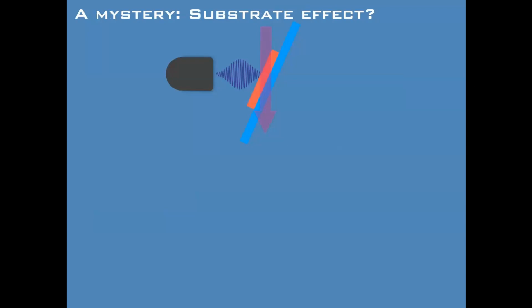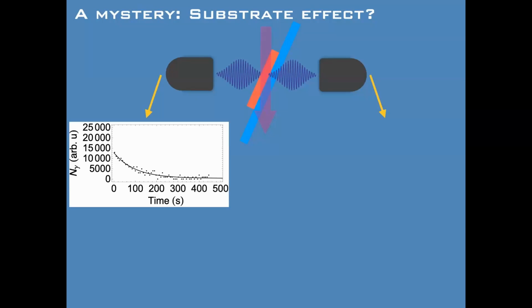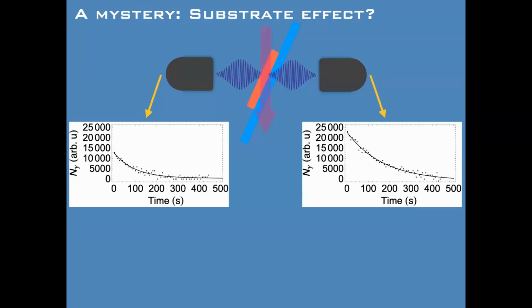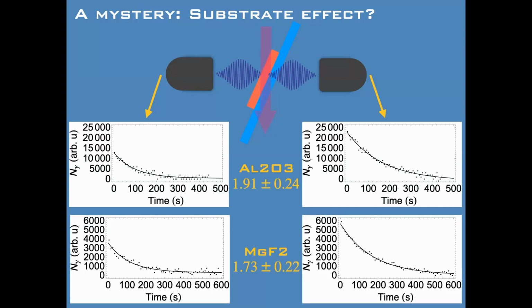All right. There's one mystery I want to throw up in case everybody thinks about such things. So this is our experiment. This was the thorium fluoride, this was the substrate. We put a detector here to collect photons. What I didn't tell you is we also have a detector over here. And so you can ask, do they see the same number of photons? And they don't. The substrate side sees about double the number of photons that the vacuum side sees, even though the substrate is like a little bit absorbing. Right? Sapphire and mag fluoride, it's about the same.